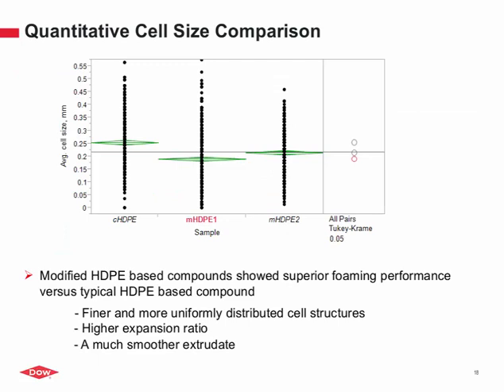If we go a bit deeper in analyzing and comparing the three systems, you can see the vertical dots are the number of data points that were taken. The control has about 250 microns, and the modified system too is clearly different, because the Tukey-Kramer analysis here shows this circle does not intersect with the control circle. So they are different, but clearly the red one is much more different. The mHDPE1 system is clearly the most different from a statistical standpoint.